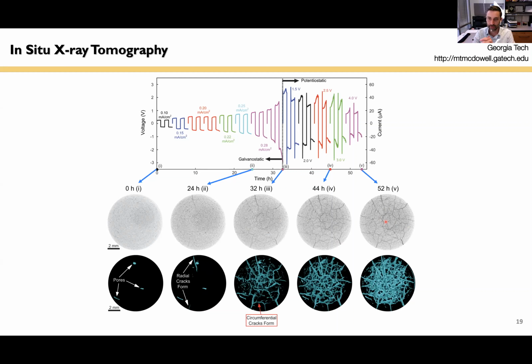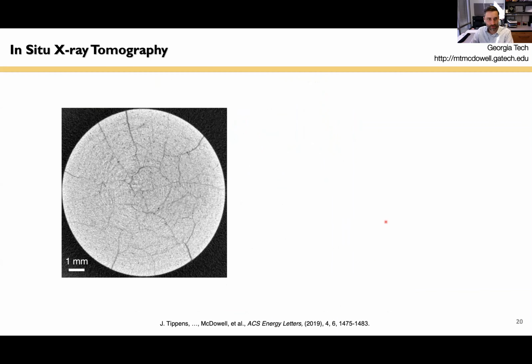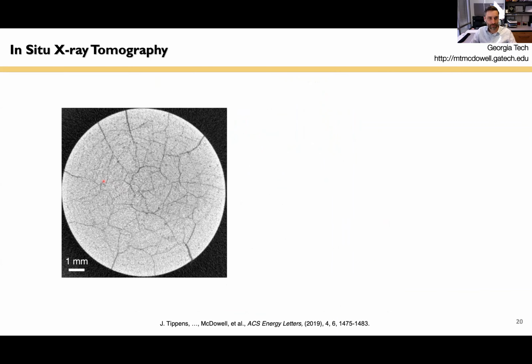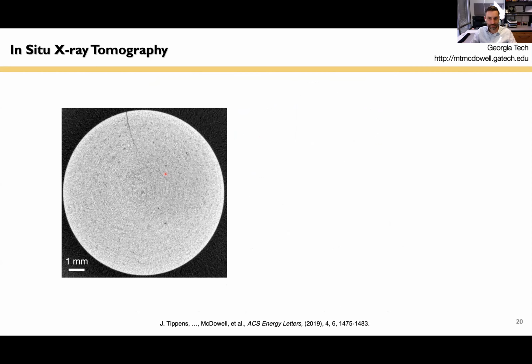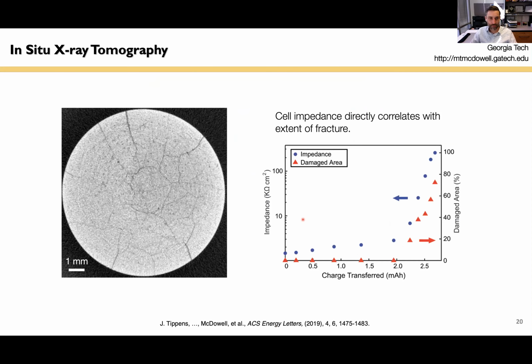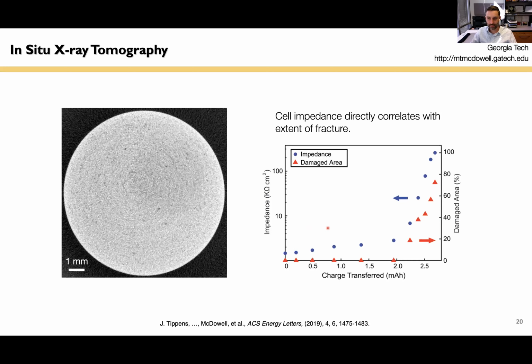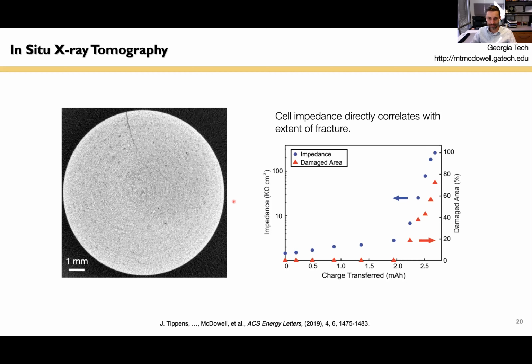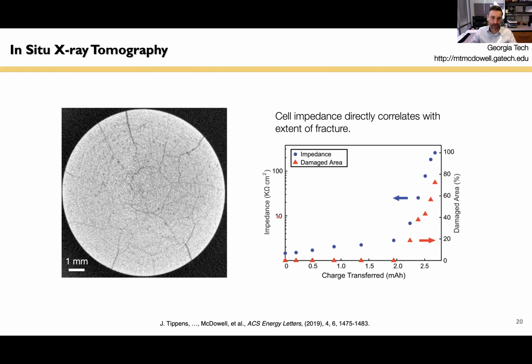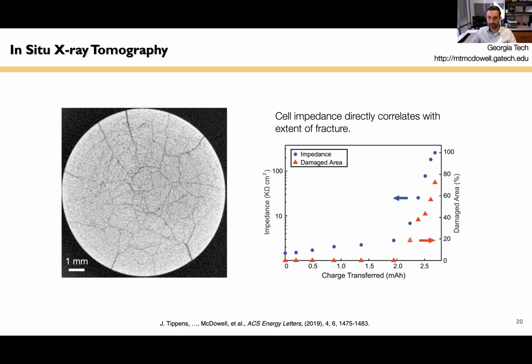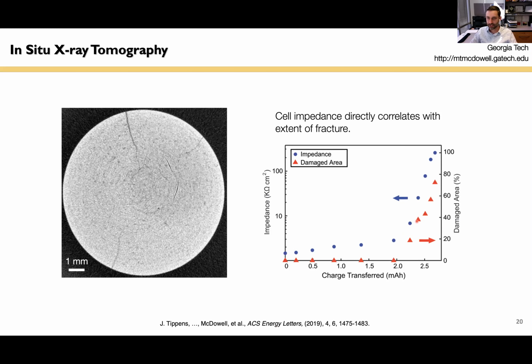But we're seeing here all these cracks are growing in, and that's different than what I showed you before. So this is a video of the fracturing process of one of these image slices. That's kind of interesting. The most important thing we learn from these measurements beyond these videos is that it's the fracture process itself which is driving the increase in impedance in these cells. And that's shown with this data here.